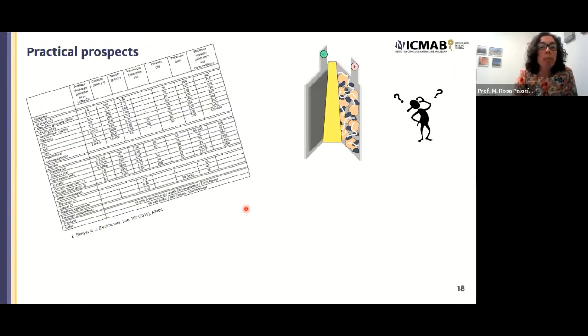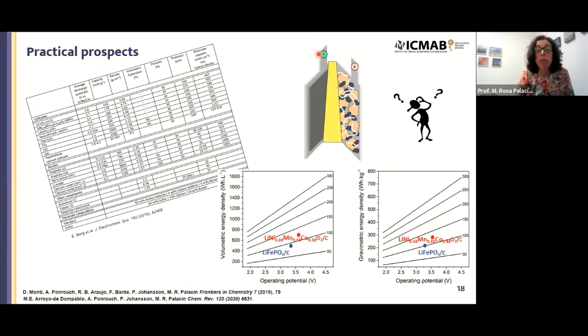So we did some calculations about the practical prospects of such technologies. We took this Excel file, which is given in this publication, a very simple calculation, just mimicking what is technologically known from the lithium-ion technology. In this case, for the positive electrode, which we would expect to be similar, a tape-casted electrode with an oxide, a binder, and carbon black. So the density, the porosity, and so on are taken from there. Then we suppose that we use calcium metal as the negative electrode, and this is what we calculated.